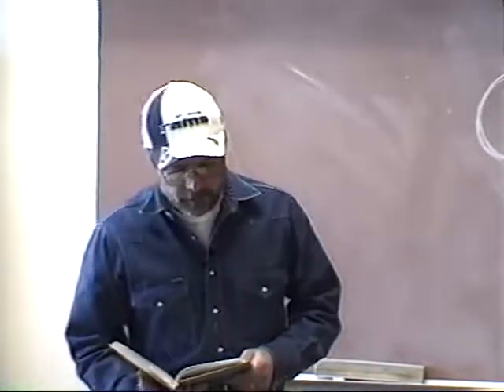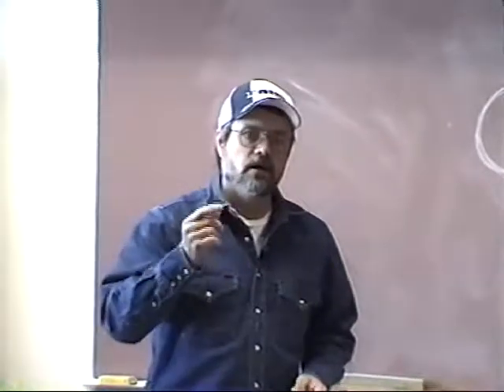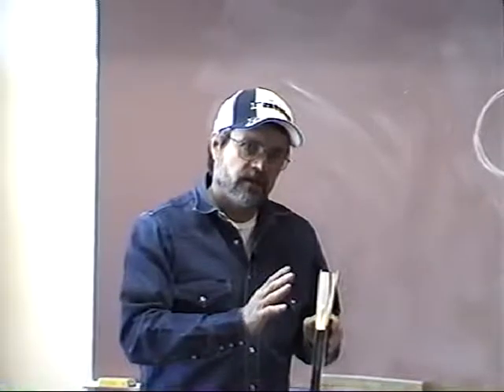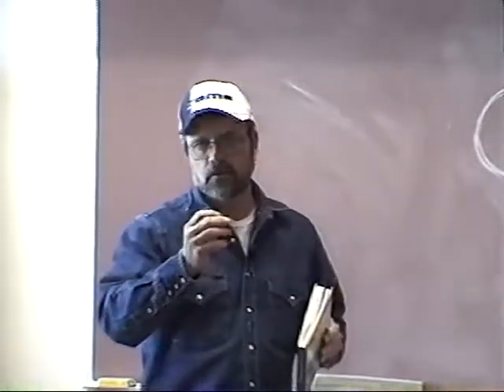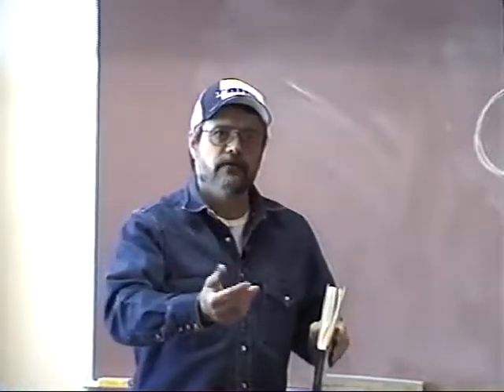Dropping down in the next paragraph, it reads, "It is important to start any weld correctly, whether tack welding or welding a longer bead. When the arc is struck, it should not be shortened immediately. Time should be allowed to stabilize the arc and allow the gaseous shield to form." And that's very important, especially in certification welding. Strike your arc, let it long arc just a little bit until you see it stabilized, especially if some of the flux has been removed or fallen off from around the tip of the electrode. Allow the metal of the electrode to burn back until it is again surrounded by flux and the arc stabilizes, and then move into your short arc length.